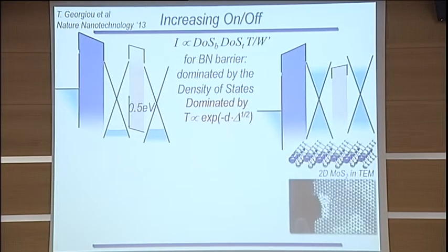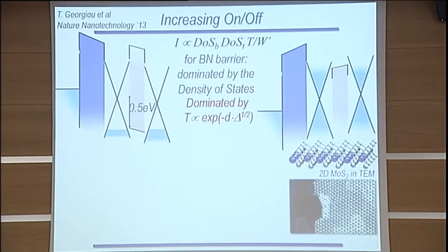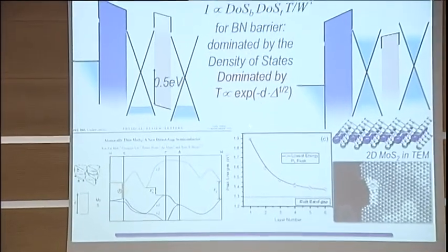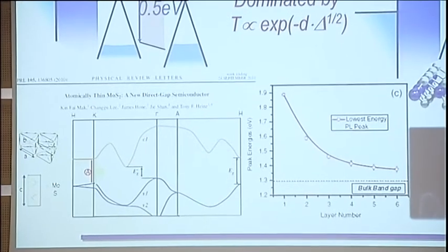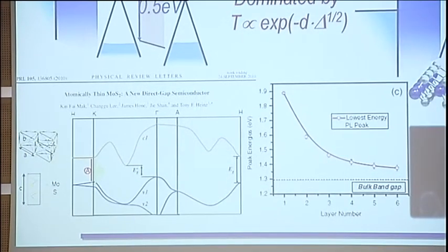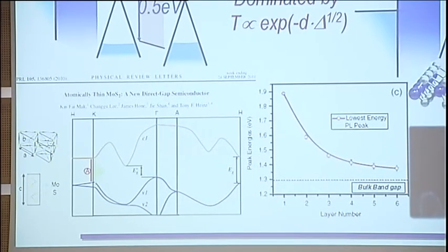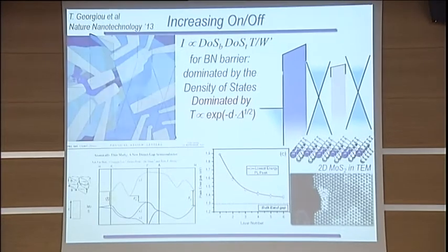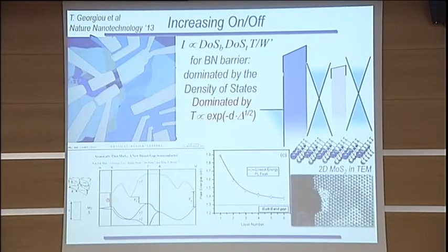And quite a few of those materials are available. It's the transition metal dichalcogenides, for example, molybdenum disulfide is one of them, and it's known that depending on the thickness, the gap there goes from 1.9 eV in monolayer to 1.3 eV in the bulk, and it really fits us perfectly because we can basically get half a volt of changes in the Fermi energy.